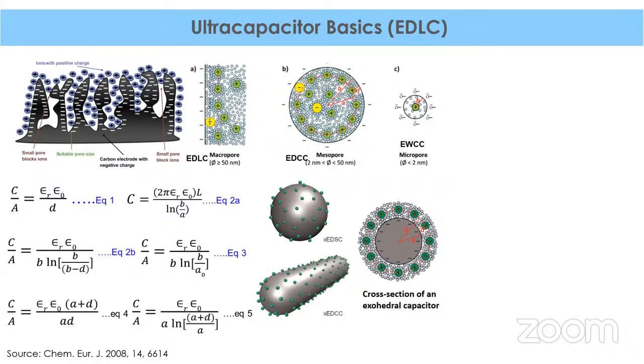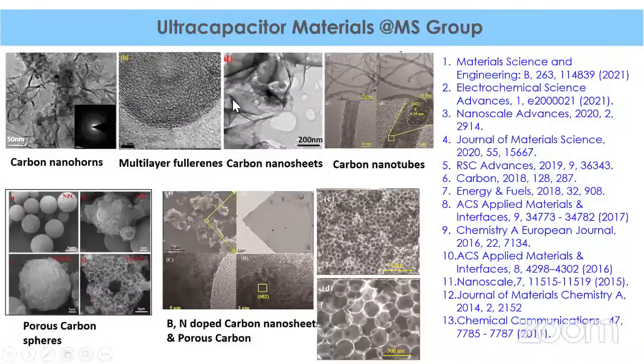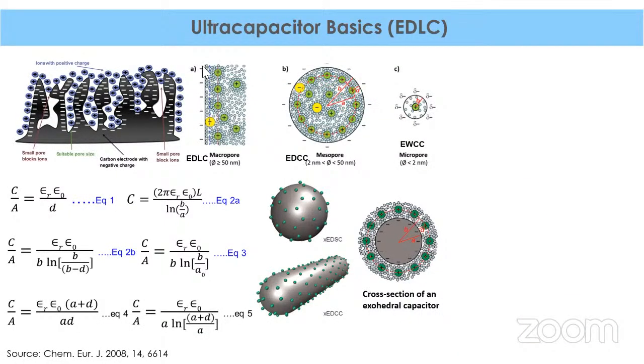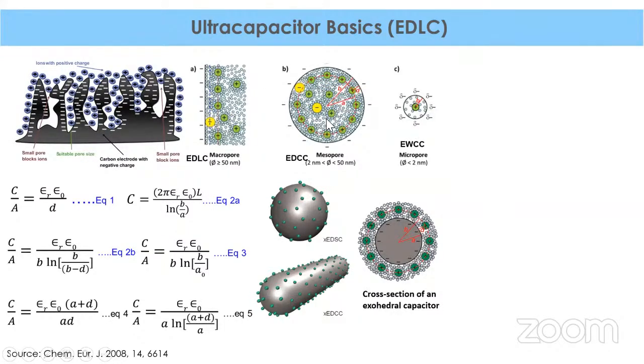Mesoporous carbon materials obtained by templating methods usually have wormhole structures with cylindrical cross sections, wherein solvated counter ions enter the pores and approach the pore walls. You can see here, these are solvated counter ions, with solvent molecules surrounding them. These counter ions enter the cylinder and arrange themselves along the wall of the pore, forming a double layer along the wall. This kind of capacitor, the researchers referred to as a double cylinder capacitor, or EDCC, instead of EDLC.